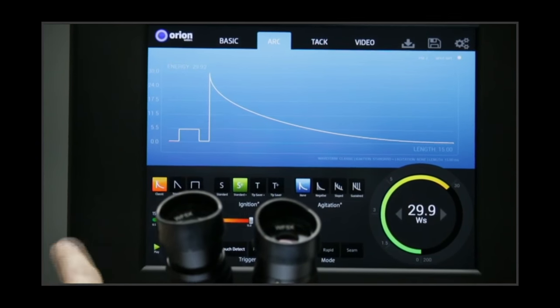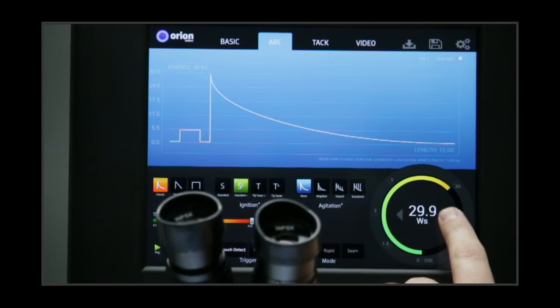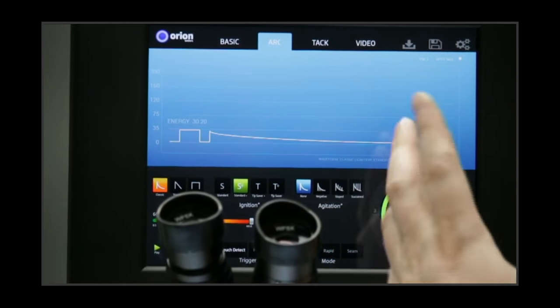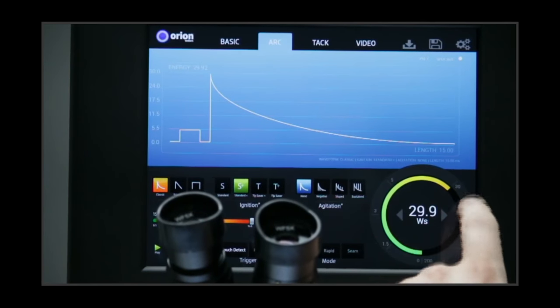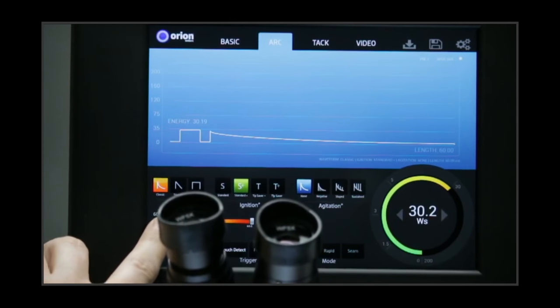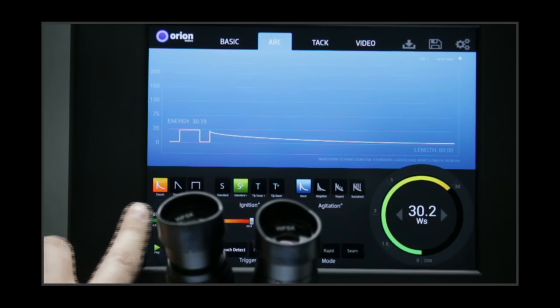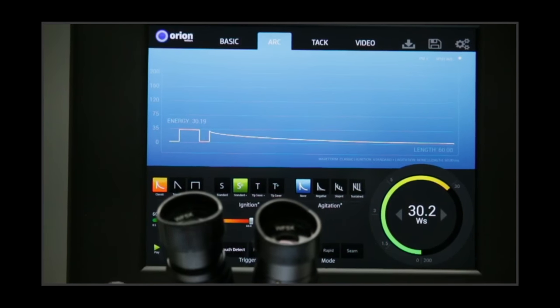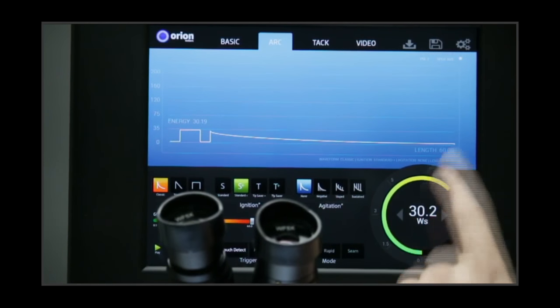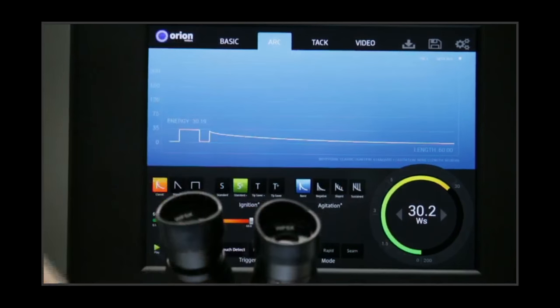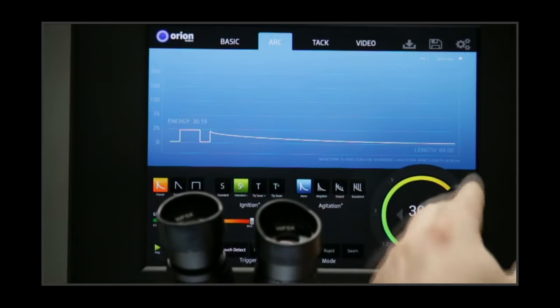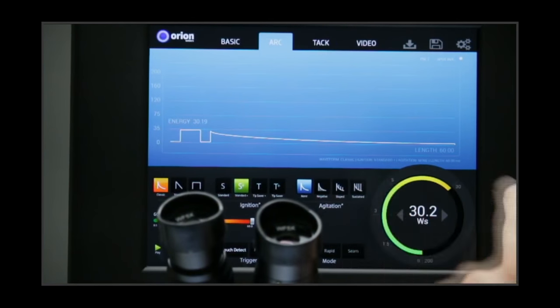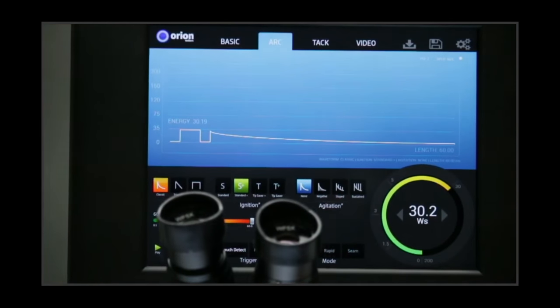And so as you can see here, if I go to silver and I go one click higher to 30, right? And now I only went one, right? As I'm here, I hit 30, and I suddenly jump from 15 to 60 milliseconds. So I'm getting 4 times the length when I'm simply moving from 29.9 to 30. And so you want to be aware of those lines on your grid. And the S has the same thing. As it goes up, the Orion automatically is going to adjust those lengths. So I'm going to go as low as I can, but still keeping that 60 milliseconds.